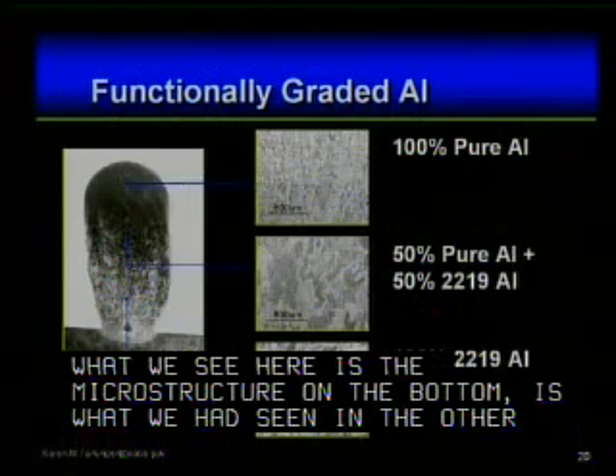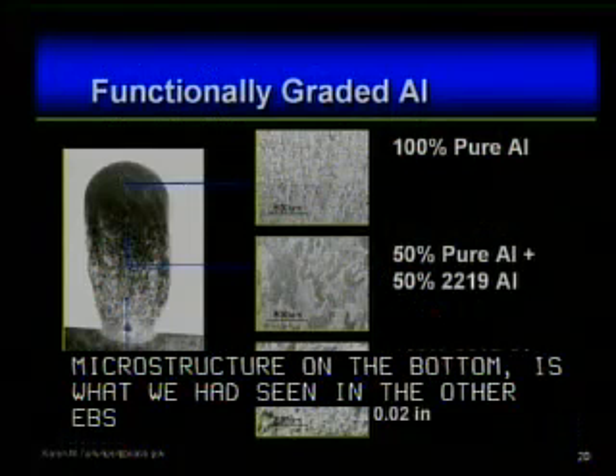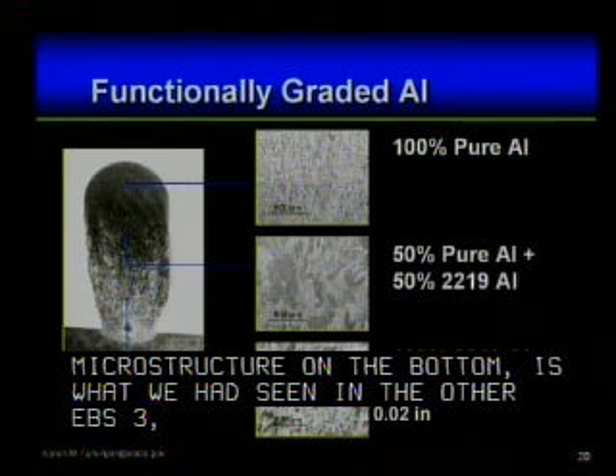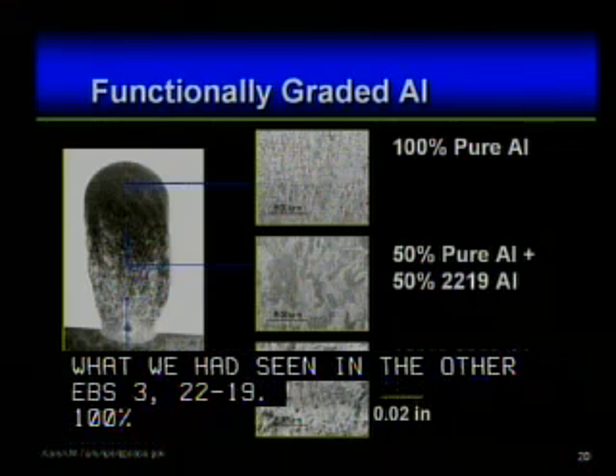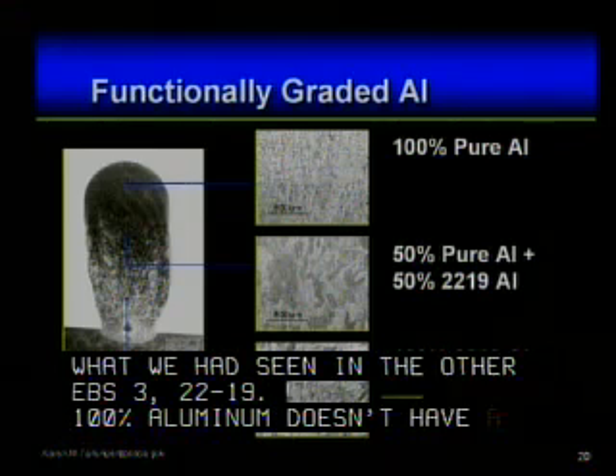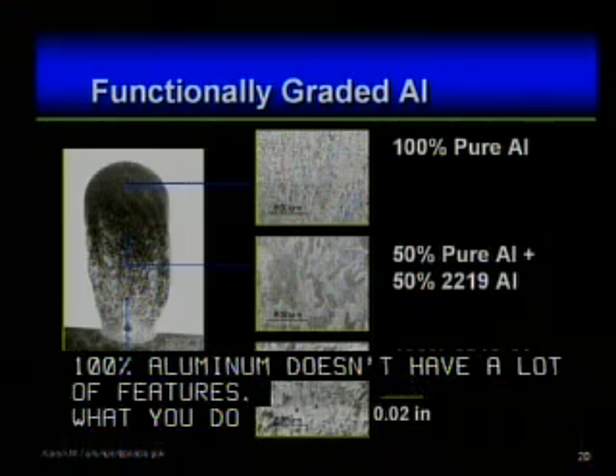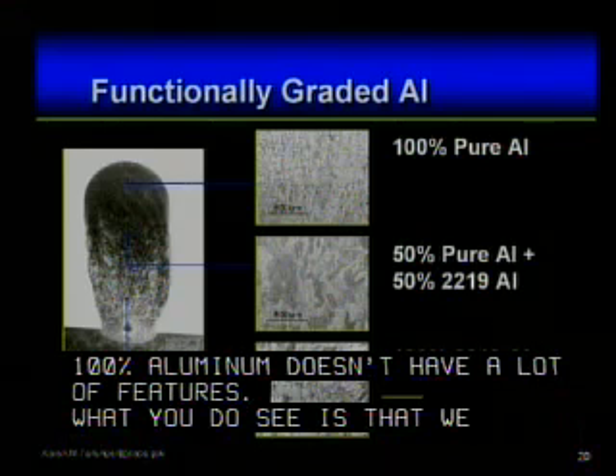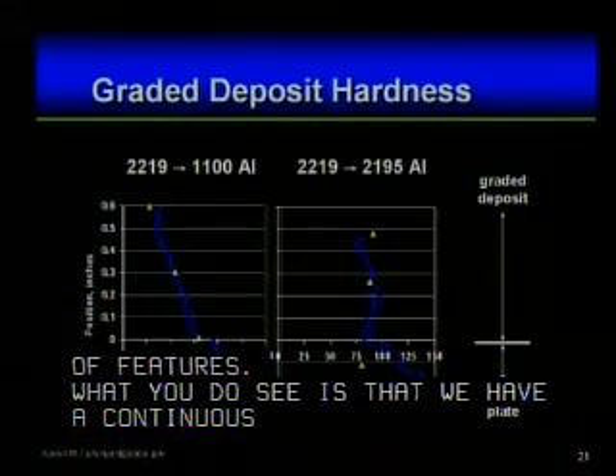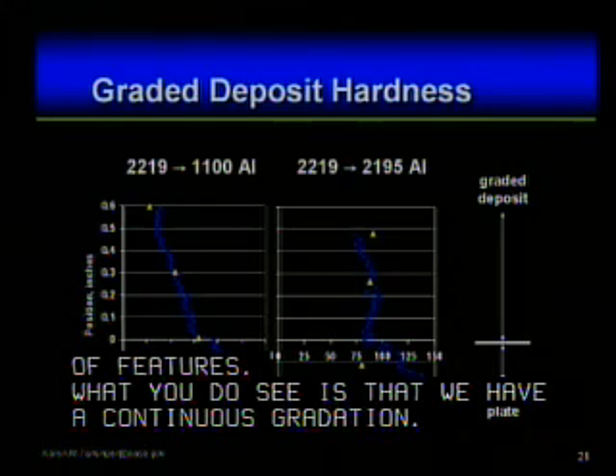100% pure aluminum doesn't have alloying additions, and so it doesn't have a lot of features. Again, that's what you would expect. And grading up through the middle, what you do see is a continuous gradation, even though this was deposited in a stepwise fashion. Next slide, please. Looking now at the hardness, it's hard to do a tensile property when your material is changing